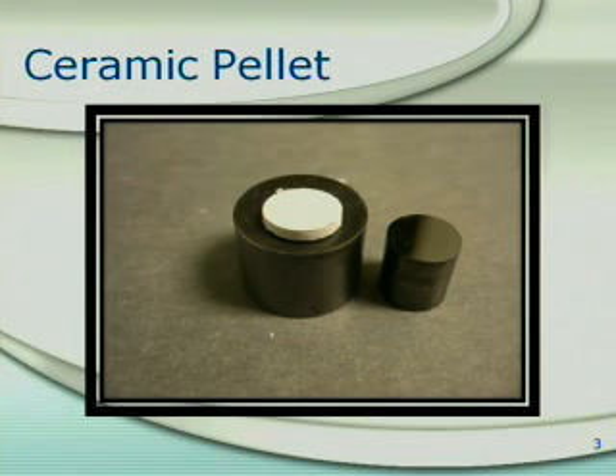The pellets are then cold isostatic pressed to 200 megapascals and are then heated to 800 degrees Celsius to remove additives. Then they are sintered at much higher temperatures to allow for the ceramic to greatly increase in density, as well as allow for any necessary phase changes to occur. The density of the pellets before sintering is known as green density, and these have been less than the 60% which is required for successful sintering.